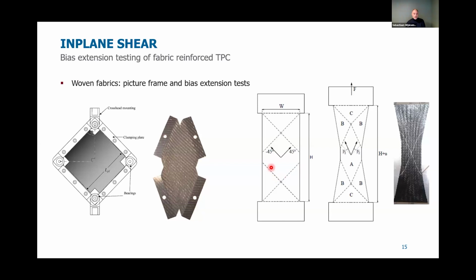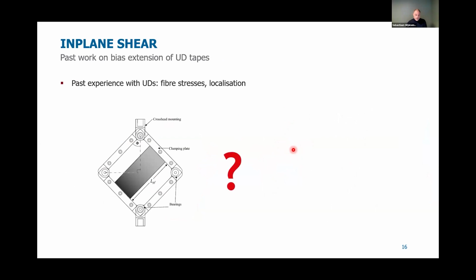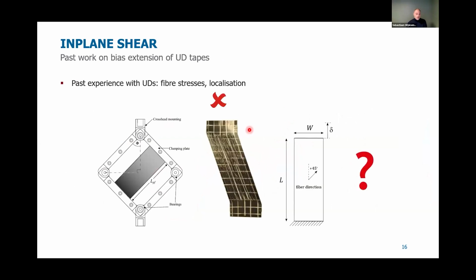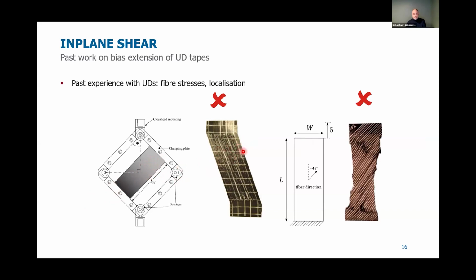The other was in-plane shear. Well, if you look at woven fabrics, then quite a lot of people have used the picture frame, to generate in-plane shear with a relatively simple analysis, or the bias extension test, which in terms of executing the experiment is a lot easier, but you have to put more effort into the analysis. We have tried both the picture frame and bias extension test in the past with unidirectional tapes. Would this work? You get enormous localization here if you try to test unidirectional materials with a picture frame. If there's a little bit of misalignment, you create enormous fiber stresses, and there's then delamination, localization, you name it. The same goes for the bias extension test at the time.